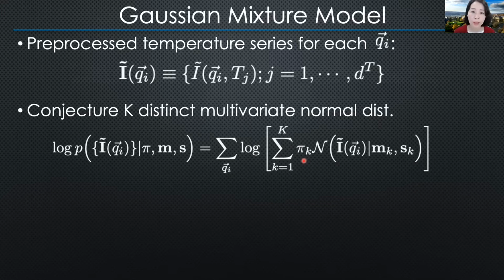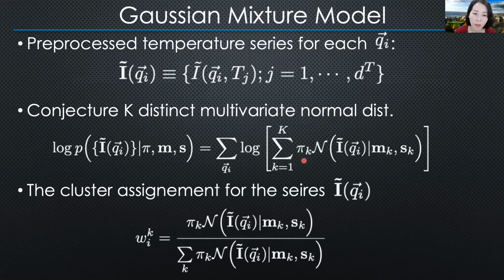So it's just like fitting. It's fitting in a large dimensional space, but not trying to fit with one function, rather allowing for multiple functions to be at play and discovering those functions. And the function is not linear or polynomial, but Gaussian. This model converges using the expectation maximization algorithm, which tries to maximize the log likelihood, the likelihood that my data came from a collection of normal distributions with the weight distribution. So you try to make it most likely, and by making it most likely, you found the distribution that best captures your data. And once the algorithm has converged, we have these cluster assignments.